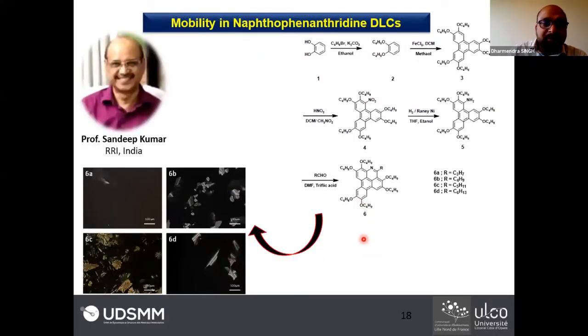The next system we developed here is naphthophenanthridine systems. Basically this type of molecules were synthesized by Professor Sandeep Kumar at Raman Research Institute. Before we go for the charge transportation phenomena and fabrication of the devices, we analyze these molecules under the polarized optical microscope. For these molecules, depending on the change in the alkyl chain length, we found that all four members show a very good hexagonal columnar phase, and they represent different optical textures depending on the different molecular ordering, which is significantly dependent on the length of the alkyl chain.